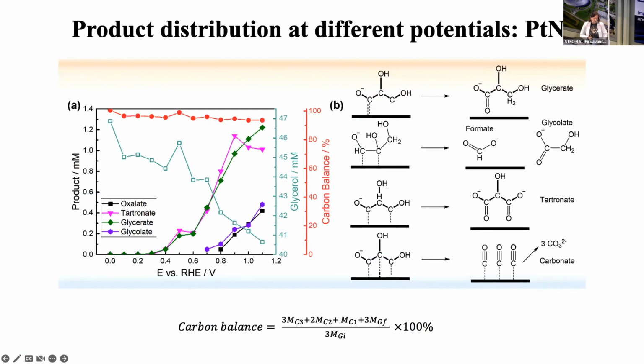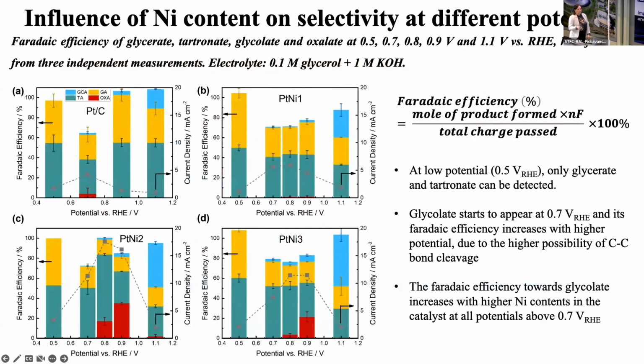So if we look at all these catalysts, what we see is that we always make this mixture of products, that we always make more C3 products at low potential and more C2 products at higher potential. And the more nickel that we have on the catalyst, the more C-C cleavage we have. So nickel promotes this C-C cleavage of the bonds, and the Faradaic efficiency, which is moles of product with electron transfer versus total charge, is changing depending on the potential.